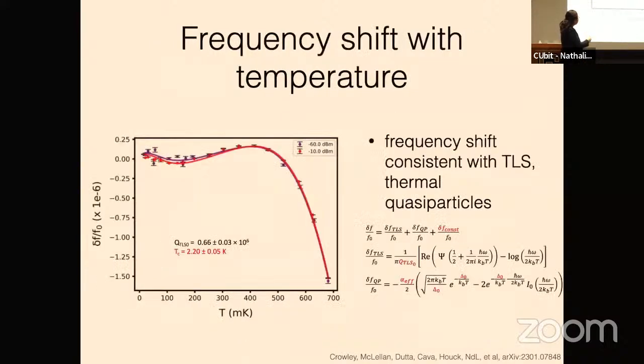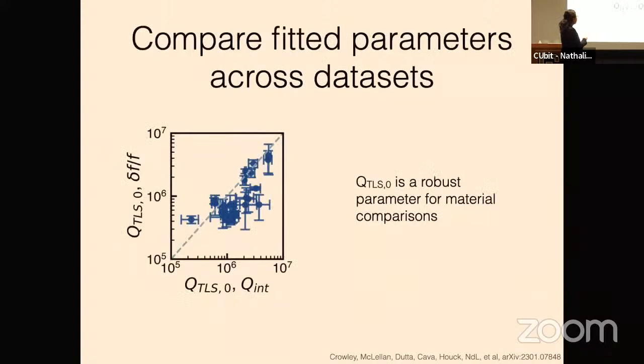We can also do an independent measurement of this TLS loss by looking at the frequency shift with temperature. And then we can look across many, many different devices. What is the Q_TLS naught extracted from one method versus the other? And we find that we get pretty good agreement. So I think this is a really robust comparison, a robust parameter to do material comparisons.